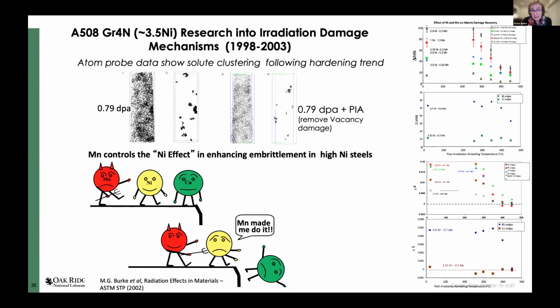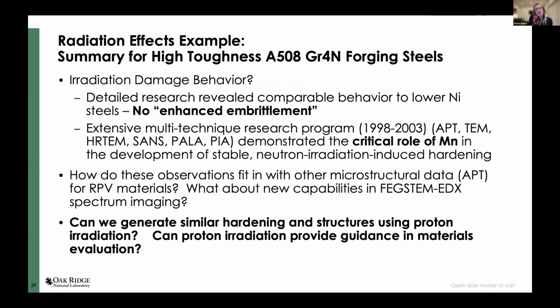But the bottom line out of all of this was that we discovered that manganese was controlling this nickel effect for the high nickel steels. So the bottom line was manganese made me do it. So that's our little manganese devil here. Okay. So do we have enhanced embrittlement? No, not really. We've identified the element that was crucial for the development of stable damage features.